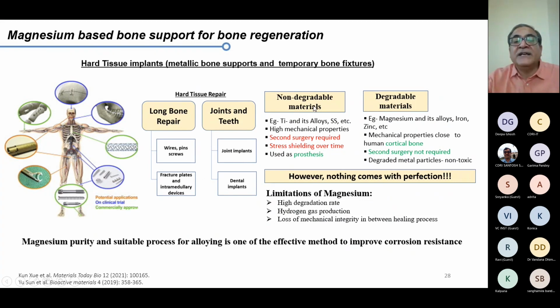So the non-degradable materials, which are stainless steel or titanium alloys, are high in mechanical properties, no doubt. But high mechanical properties are not necessarily a major advantage, because they can cause what you call stress shielding over time. That means they will loosen, because the mechanical property of the bone with these types of implants is not matching. You need a second surgery in that case, because you have to take the metal implant out.